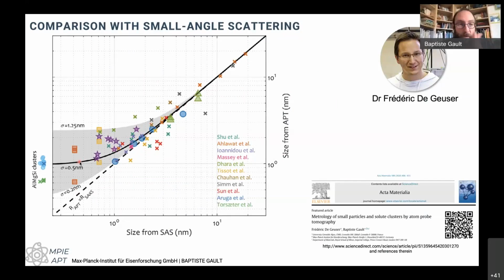But below a nanometer, these trajectory aberrations are going to make things much more complicated in terms of measuring the size. We're still detecting the atoms. We can still derive a composition locally, but there will be a bit of intermixing between the matrix and the particles. So sometimes we have to be quite careful with the way we interpret the data that we get.